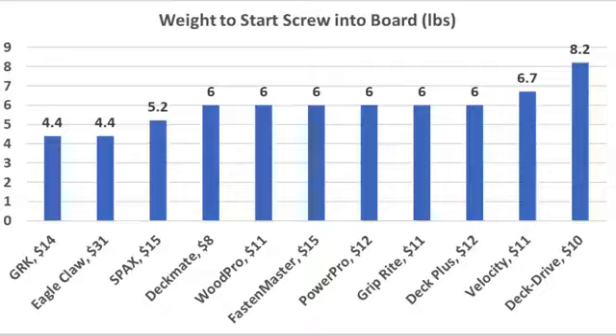After testing all the brands, the GRK and the Eagle Claw came out on top and needed the least amount of downward pressure at 4.4 pounds. The SPAX also performed very well at 5.2 pounds. Most of the other brands needed 6 pounds of downward pressure to get the screw started.